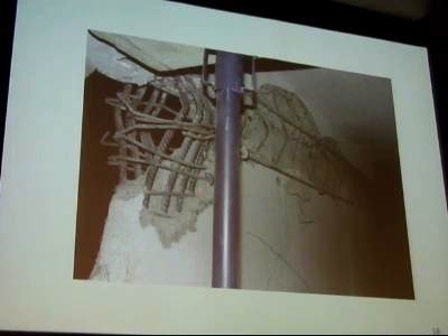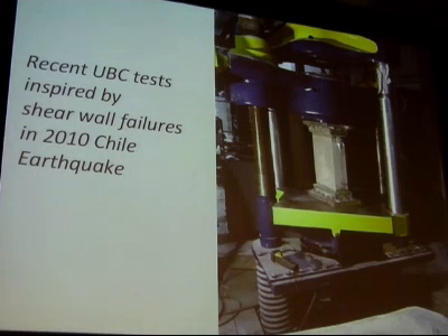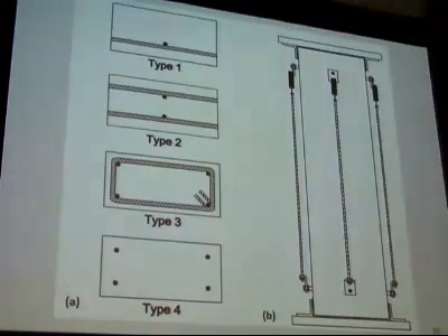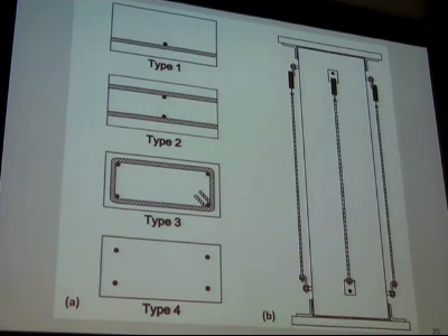So as Dennis already mentioned about the lack of confinement and anchorage issues, as I said, I want to focus on one failure mechanism, which I believe is very important, which is flexural compression failure of these walls. These were some little tests we did at UBC, and this is what the specimens looked like. I just want to focus in on two of them, the type 3, which has some very nominal ties, not what you would call confinement ties, but very light ties, the kind of thing you'd put in a non-seismic element. Just minimum column ties. And the type 2, which doesn't have anything connecting the two layers of reinforcing steel. And there's two layers of small bars in a 150 millimeter wall, which is what we saw in Chile.